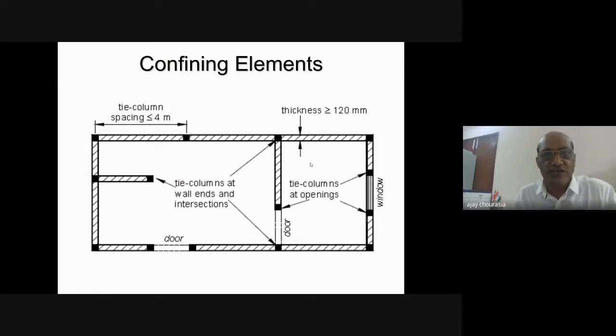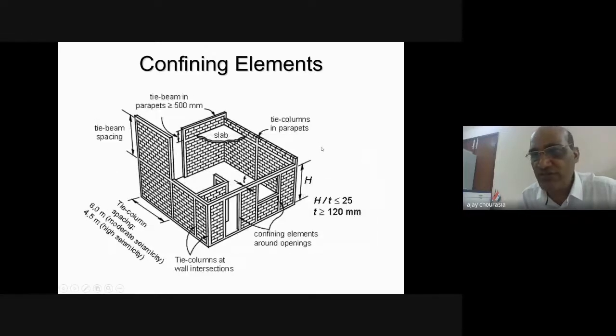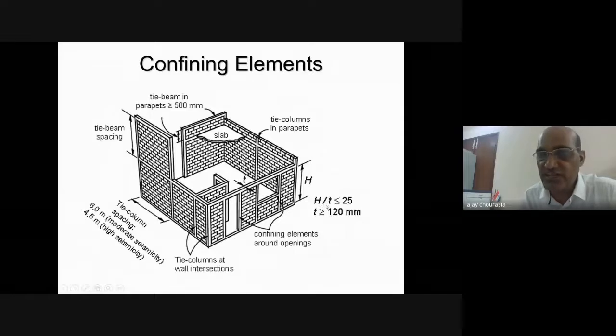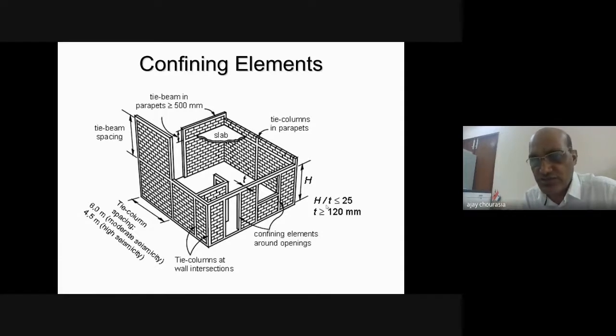Before going into further details, there are general planning aspects which should be looked into in a confined masonry building. The tie columns need to be provided at all intersections, all corners and around the openings. The spacing between the columns should be limited to a maximum of 4 meters. For a single story building, you can opt for even 9 inches, 230 mm thick brick masonry, but for higher stories you have to increase the wall thickness. In this, you also have to consider the slenderness of your wall panels. The slenderness is governed by h by t, height to thickness, or l by t, length to thickness ratio, which should be less than 25, and the minimum wall thickness should be more than 120 mm.